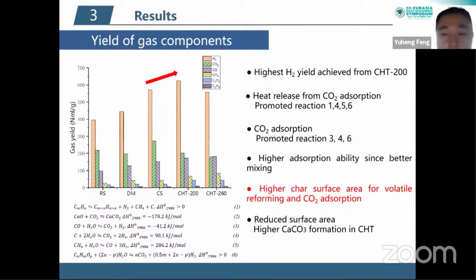And we found in the BET results that the surface area for the CHT is much higher compared with the raw materials, because of the in situ reforming that increased the hydrogen content for the CHT. And for the CHT at 260 centigrade, we also found that the surface area was reduced, which is not helpful for the decomposition of the tars and for the other gasification processes which could produce hydrogen.